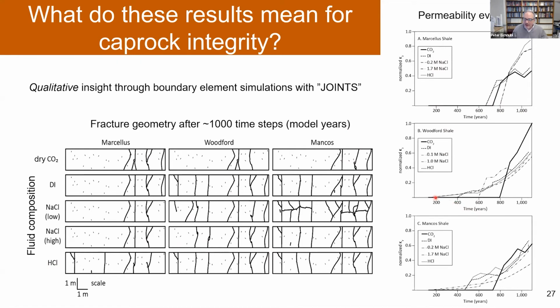we see that in the water-rich environments, the fracture growth starts early, and then permeability increases up to a point. If we do it in a dry environment, nothing happens for a long time, but then quickly the fractures grow across, and at the end, actually, the permeability is higher in the dry CO2 case than in the water-saturated cases. Okay, so that's very interesting. So even though the fractures start leaking earlier, at the end the permeability is higher for the dry case. The Mancos shows the same thing.